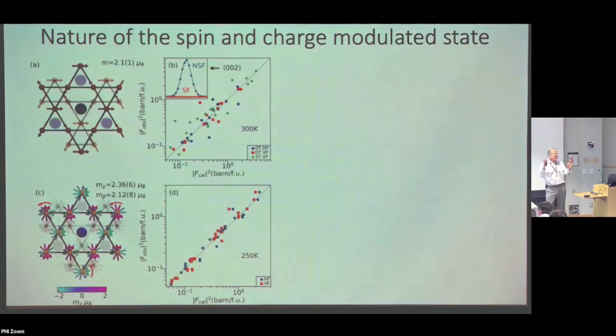That's absolutely crucial. Had it been clockwise rotation, then I wouldn't have had all of this anomalous Hall effect at all. So it's all tied to the handedness of the rotation. Because of that, the symmetry is really that of a ferromagnet, and because of that, the Dirac point is split into Weyl points when this magnetic structure develops, and because of that, I have anomalous Hall effect. So it all kind of hangs together like that.